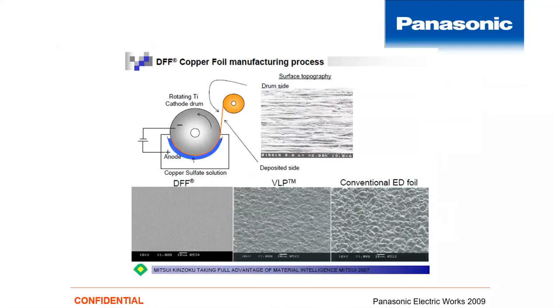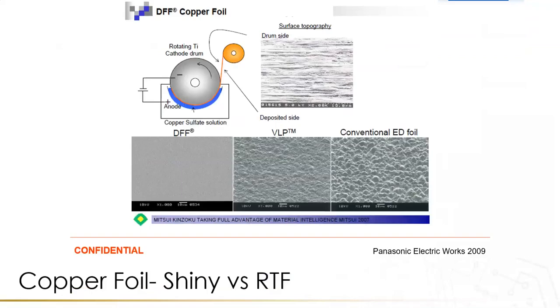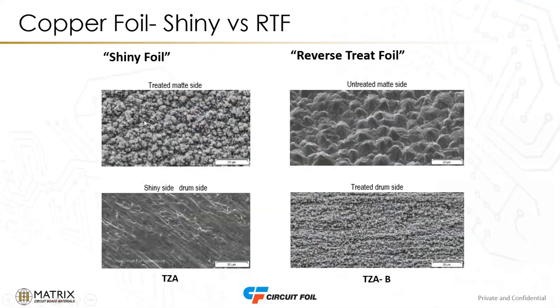So there are different topographies. Years ago we were looking for bond strength, so we wanted more topography, more like the conventional electrically deposited foils. But now we're looking at improved signal performance, so we're looking at lower profiles, which would be VLP or HVLP, and this is showing an even flatter foil, almost no profile. But the other option available is RTF. So this gives you an idea between the shiny and the RTF.